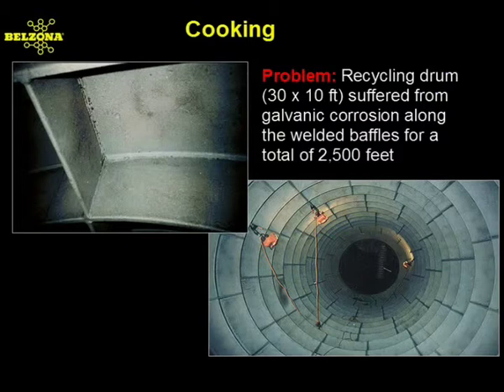This 30-foot by 10-foot recycling drum suffered from galvanic corrosion along the welded baffles. This drum operates at a pH of 10 and a temperature of 120 degrees Fahrenheit. After only 3 years, this $9 million unit had 70% of its 2,500 feet of liner weld corroded.